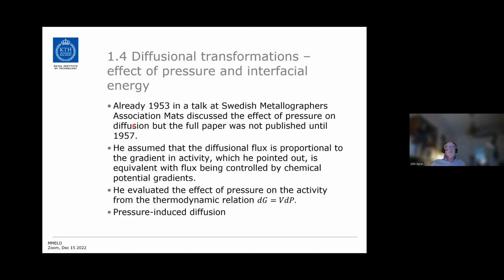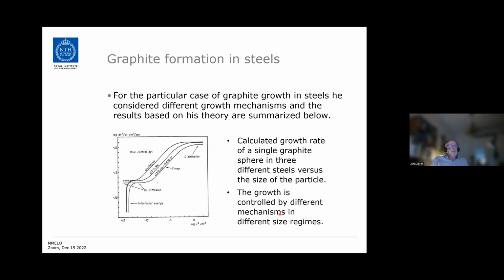Now he assumed that the diffusional flux is proportional to the gradient in activity. And he realized that this was equivalent with the flux proportional to the gradient in chemical potential, which is what we use now. And he evaluated the effect of pressure on the activity from this well-known thermodynamic relation, and that gave rise to pressure-induced diffusion. So he applied that to graphite formation in steels.